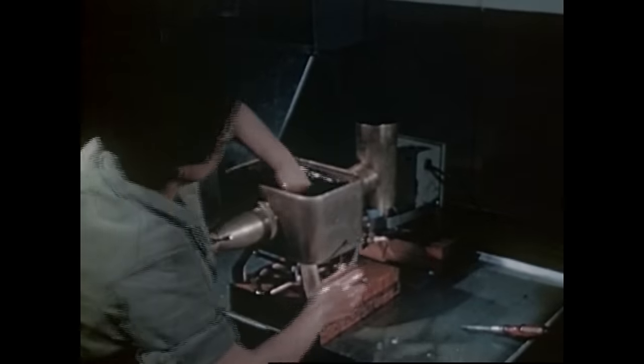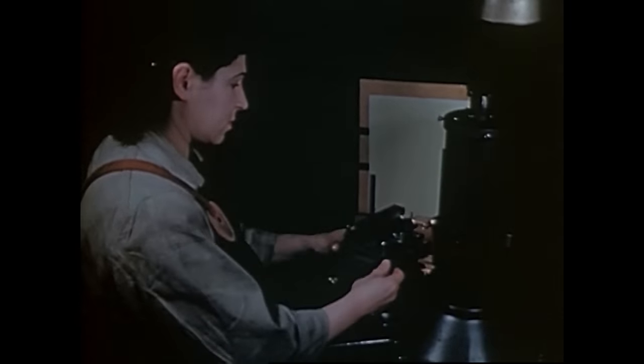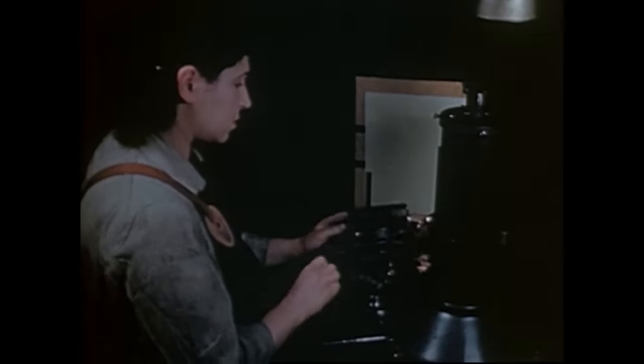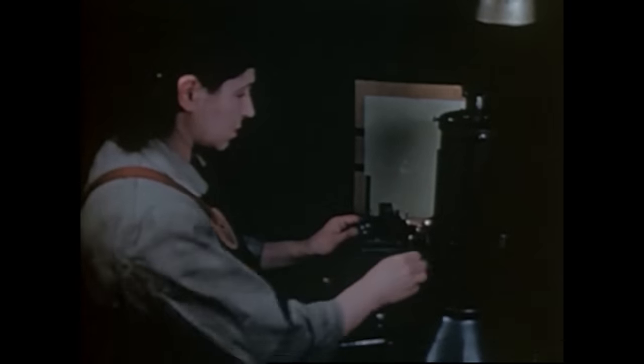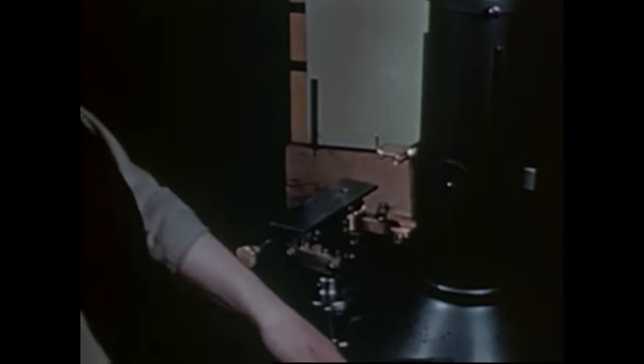For final and still greater accuracy, adjustments are made by means of X-rays in the darkroom. The X-ray machine is so set up that when the quartz is tilted to its exact position for sawing the BT cut crystals, a characteristic pattern of spots is reflected from the atoms of the crystal, making a sort of picture of the positions of the atoms. These spots are not visible to the camera, but appear on the screen before the operator. When satisfied that the position is correct, the operator locks the jig in proper adjustment and places it on the shelf ready for the wafering saw.